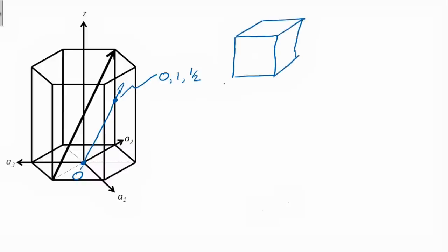So when we translate it back by one A lattice parameter in the positive A2 direction, it now originates in the conventional origin, right in the very middle of the basal plane and travels out. But you'll notice that it travels two steps before it makes one rise in the Z direction. Therefore, it's going to exit our unit cell at half the height. So now we've got this vector that's going out straight along the A2 direction with a rise for that one step in the A2 direction, a rise of one half. So that vector in our three axis notation would be, well, it's got no component in X, it's got one in Y and one half in Z. So we've got zero, one, and one half, multiply across by two, zero, two, one.